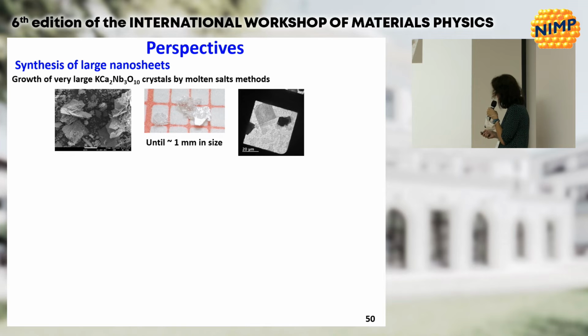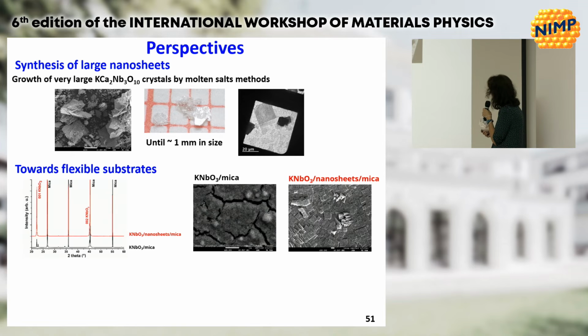So some perspectives for this work. First, we would like to have larger nanosheets to improve our properties a little bit, and we have some first results obtaining large crystals by molten salt methods. Also, we would like to go towards flexible substrates. Here I have an example of a potassium niobate film which was grown on mica. Directly on mica, we have something which is not really good, as you can see on this micrograph. But if you insert nanosheets on the mica, then you have a preferential orientation and a very good microstructure of the films. So mica is transparent, easy to delaminate, and we can transfer the whole stack onto something else, like a polymer, for instance, or silicon again.